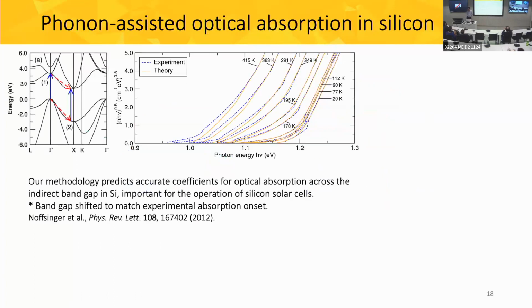So with all that together, we find that we can predict indeed accurate phonon-assisted optical spectra across the indirect bandgap of silicon, which gives us the absorption edge now across the indirect bandgap. I need to note here that we have slightly shifted the bandgap to match the experimental absorption onset because we don't have such accuracy with DFT or the GW method to predict these small variations to the bandgap.